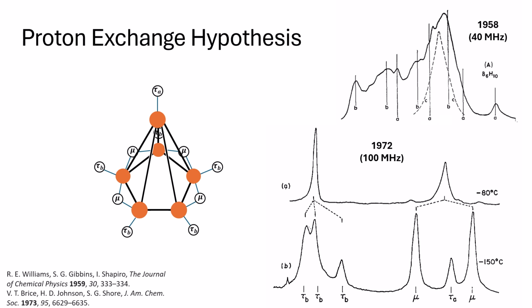Subsequently, we can see that the upfield chemical shift peak, which corresponds to the terminal hydrogen atoms on the basal boron atoms, is split into 3 different peaks at a lower temperature, corresponding to 3 different chemical environments of the basal boron atoms. Furthermore, the more downfield peak split into 2 peaks representing the 2 chemical environments for the bridging hydrogens, and also revealing a hidden peak for the terminal hydrogen atom on the apical boron atom.